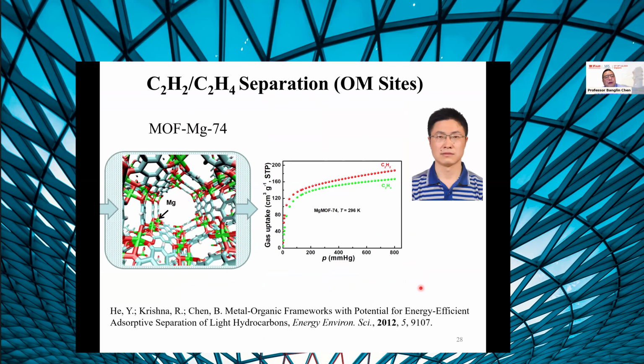And in another example, as mentioned, MOF-74 can take up a large amount of acetylene. However, this also takes quite a large amount of ethylene as well. The uptake is quite high, but here the selectivity is not good. This is another example for this separation. So the ideal one is to have both high uptake and high selectivity. That we call the trade-off, because typically high uptake will sacrifice selectivity, and high selectivity will sacrifice uptake.